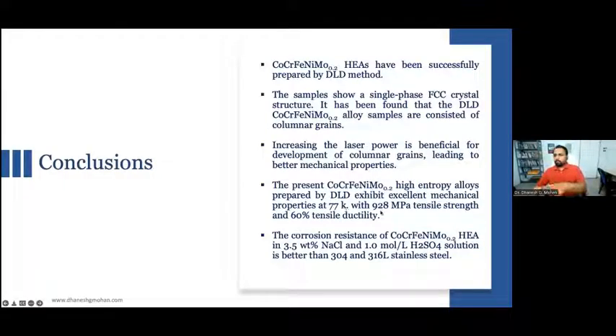And for the mechanical testing, we found out that the highest strength of the metal is 928 megapascal. And in corrosion testing, we found that compared to all the other metals, this high entropy alloy has a superior corrosion resistance property.